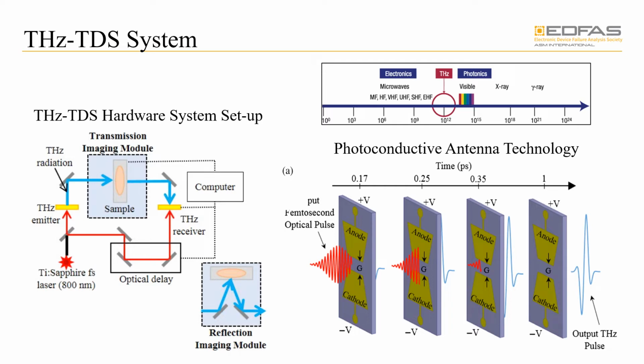For the reflection mode terahertz TDS, the terahertz emitter and detector will be placed on the same side of the sample. The signal will penetrate into the sample and get reflected by the interface of different materials, and this detection will collect the signal amplitude as well as its change with time and generate the terahertz spectrum.